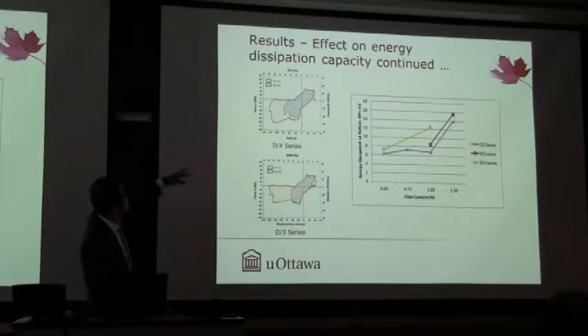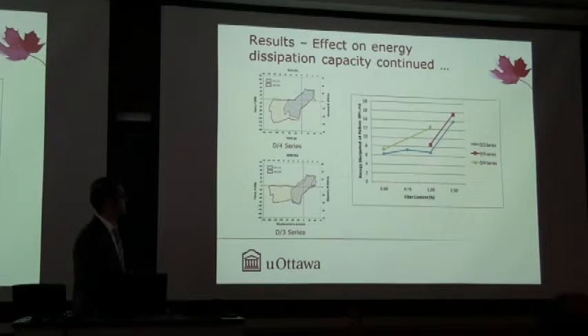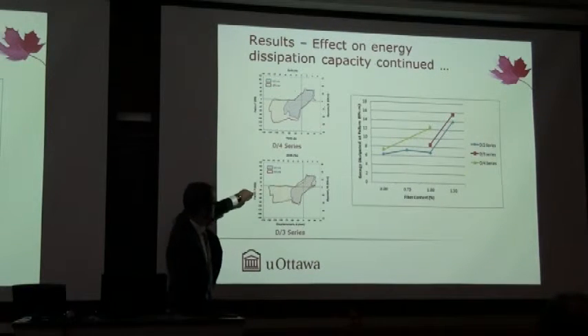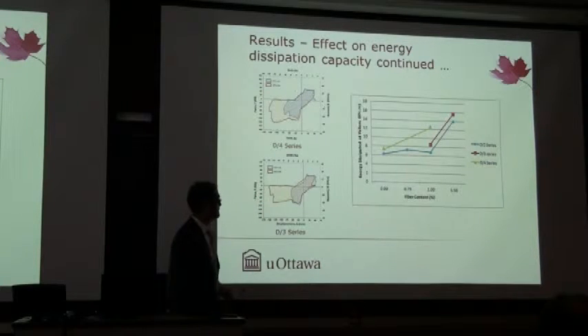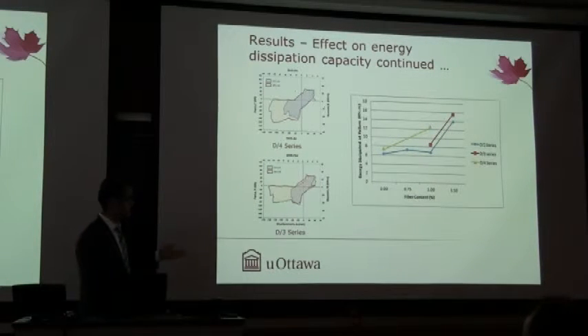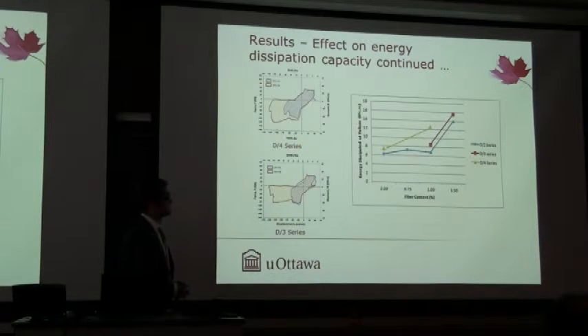As you can clearly see in the diagram, these are diagrams for my other beams. In these diagrams, the hoop spacings are the same, and we are only increasing the fiber content. As you can see, the area under this diagram, which is my D/3 beam with 1.5% fiber, is a lot larger than my D/3 beam with 1% fiber. And again, in that diagram, you can see the improvement in energy dissipation capacity of the beams. The only exception was my D/2 1% specimen, which has a slightly lower energy dissipation capacity compared to the specimen with 0.75% fiber.